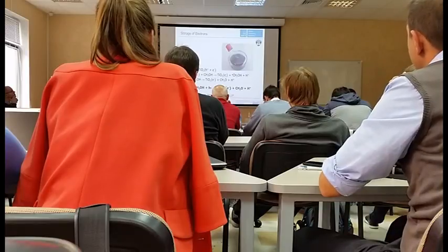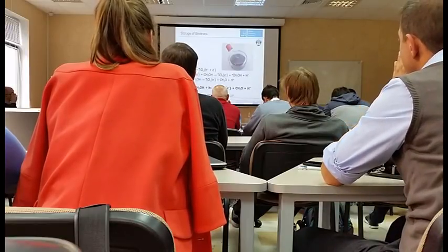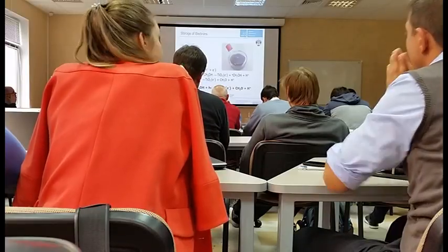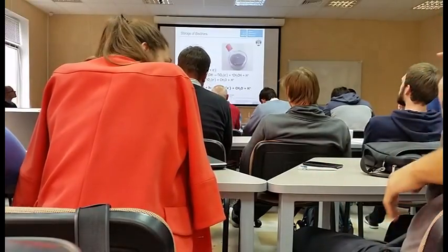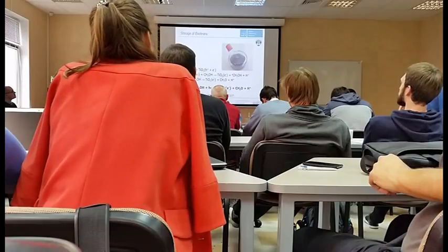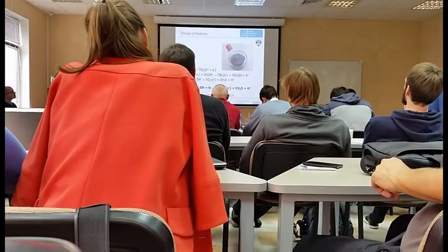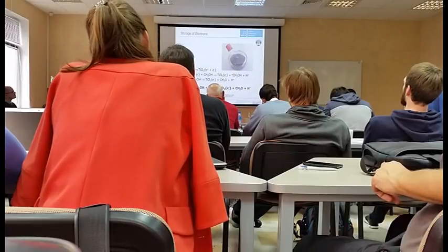You prepare this TiO2 and you illuminate it in the absence of oxygen and in the presence of the alcohol. The alcohol is oxidized, I showed you this before, and the electrons have nothing to react with because you don't put in a catalyst, so you don't form hydrogen.